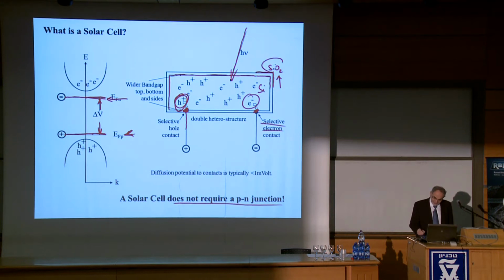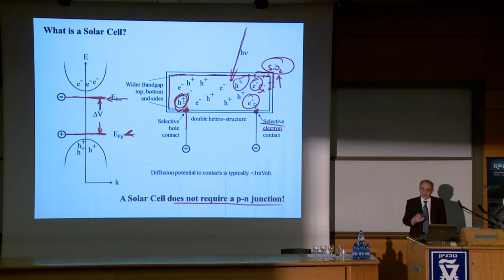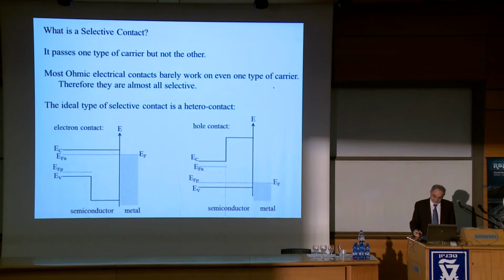First, I also have to show you why we use the silicon dioxide. We really don't want the electrons and holes to recombine at dangling bonds. The surface has many dangling bonds. Okay, and so you have to coat the surface. This is a standard thing in electronics. You coat the surface with a wider band gap material so there are no dangling bonds. And then the wider band gap keeps the electrons and holes in. So how to make a selective contact? Well, here is an example. Suppose you have a heterojunction like this, and the electrons go freely to the metal, and the holes, they don't make it.